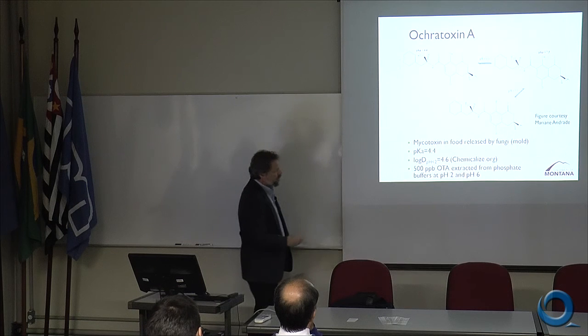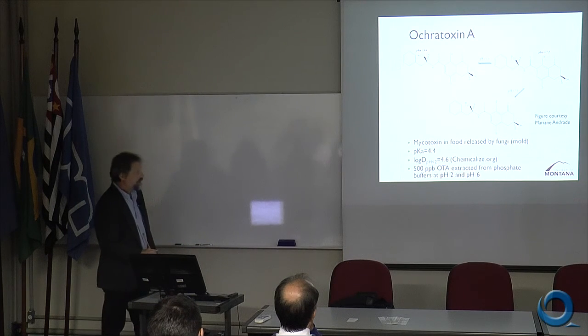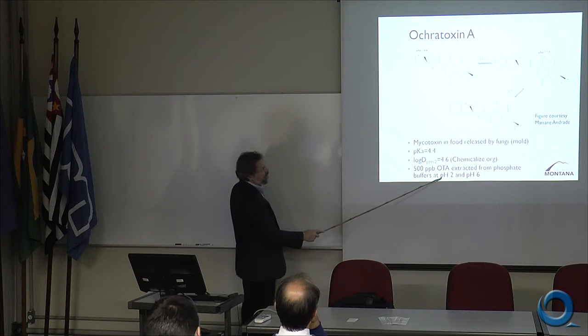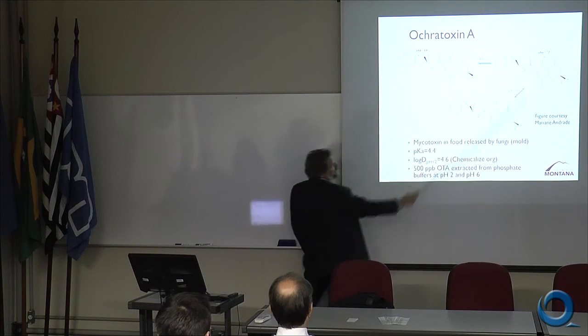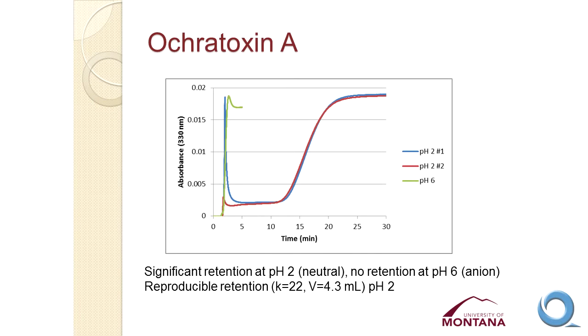So we looked at 500 parts per billion ochratoxin A. We looked at 2 different phosphate buffers at pH 2, where it's in this form, and pH 6, where it's primarily in that form. And I'm showing the raw data here. So the red trace and the blue trace are both at pH 2, non-ionic, 2 separate injections or 2 separate analyses. You can see the reproducibility of the analyses. You can see that we're getting significant retention of the compound for 10 minutes or so. And in fact, the inflection points out here, 17, 18 minutes or so.